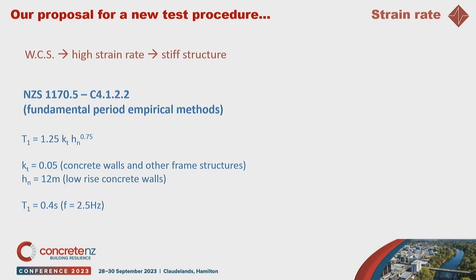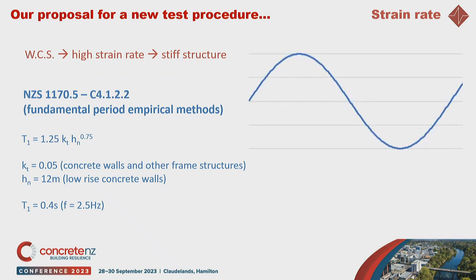Because we are implying that the strain rate comes from an earthquake, that comes from a stiff structure to have a high strain rate. So worst case scenario should be when I have a stiff structure which is not too high, so a low-rise concrete wall structure. Let's say something that has a fundamental period around 0.4 seconds, 2.5 hertz, which is quite fast, but that's a full cycle.